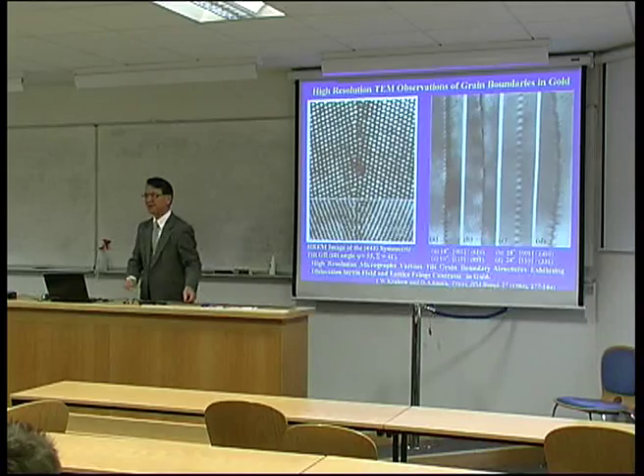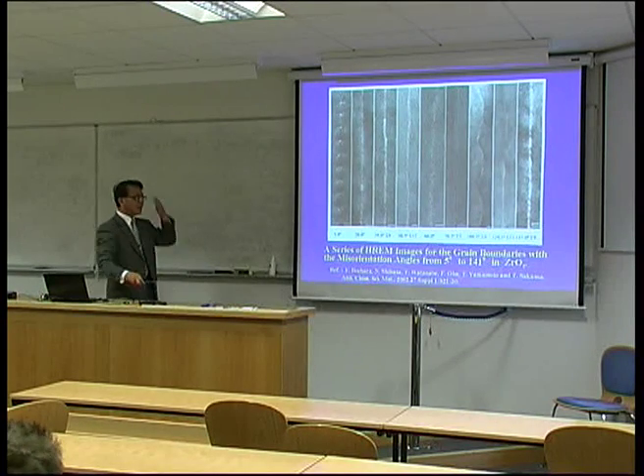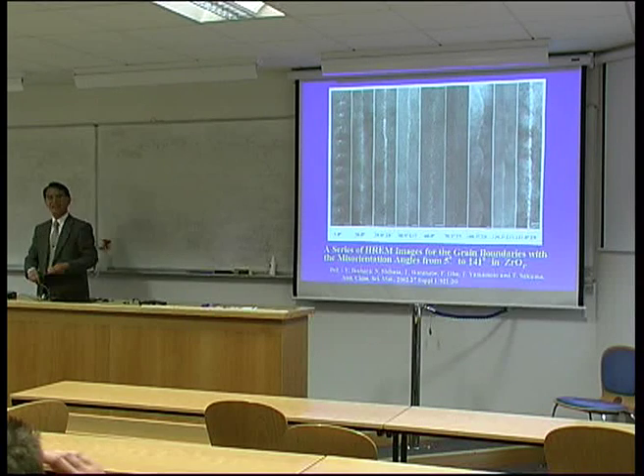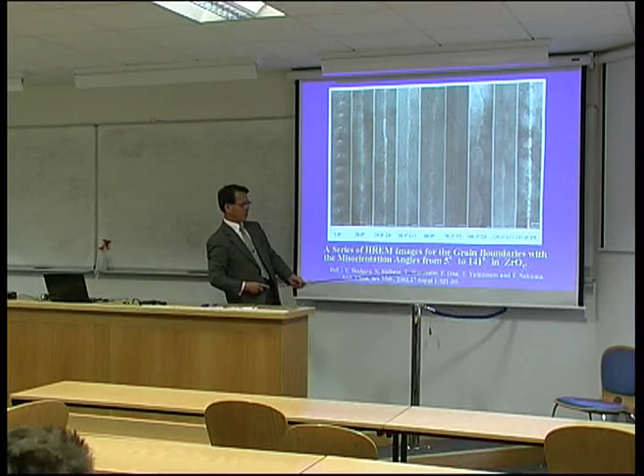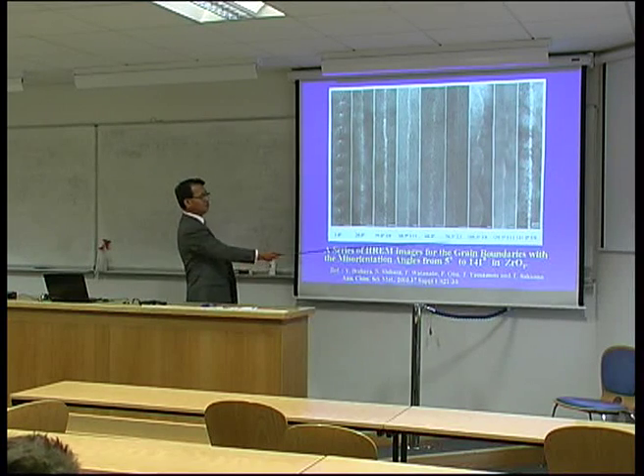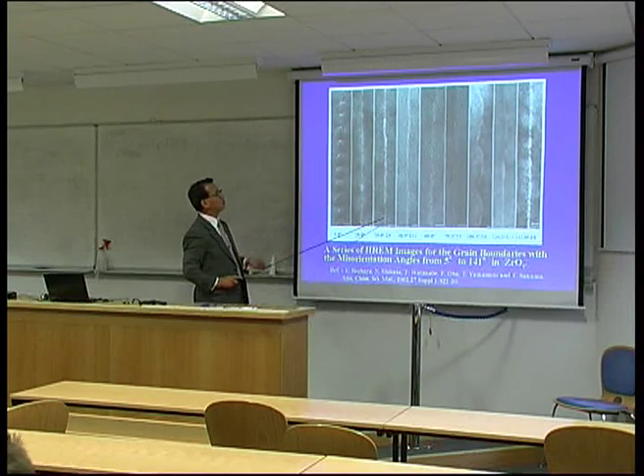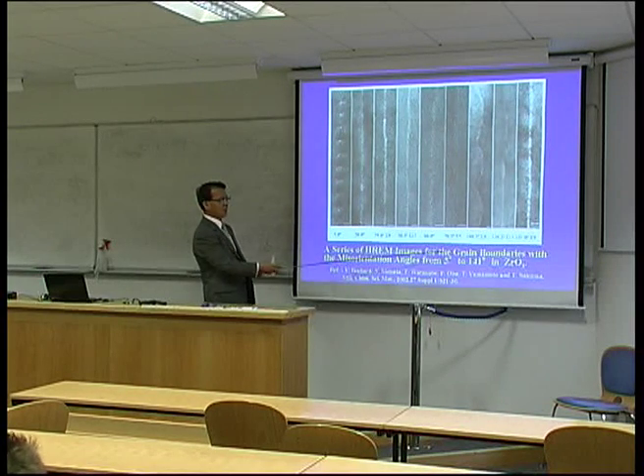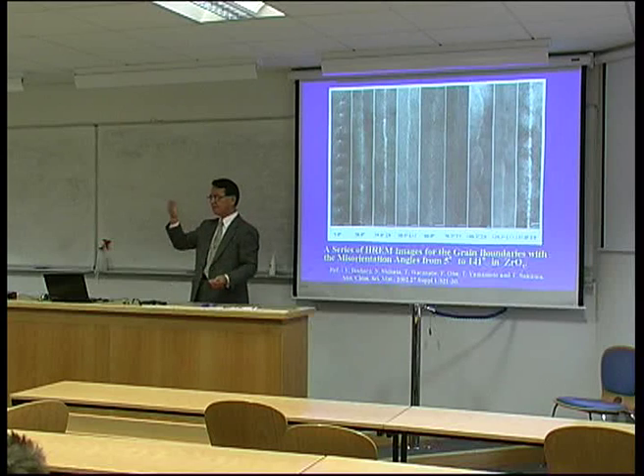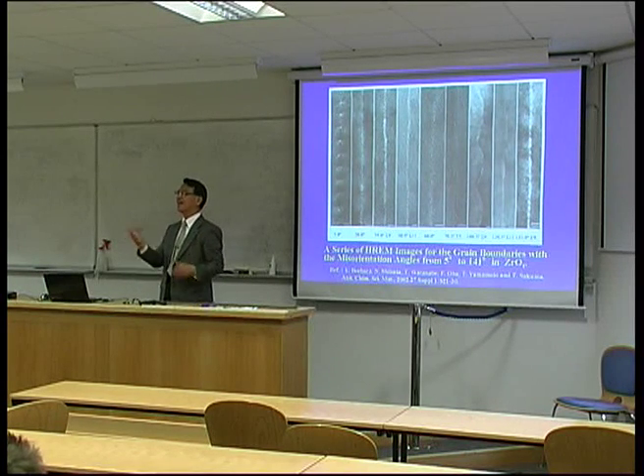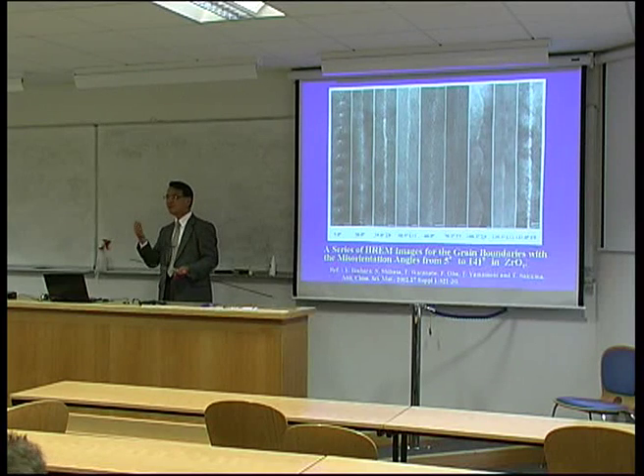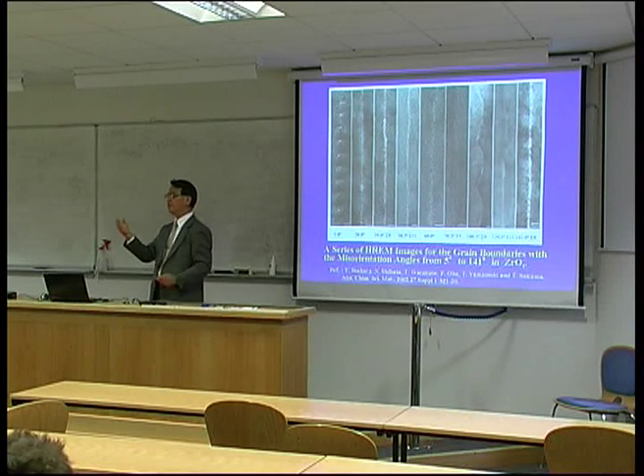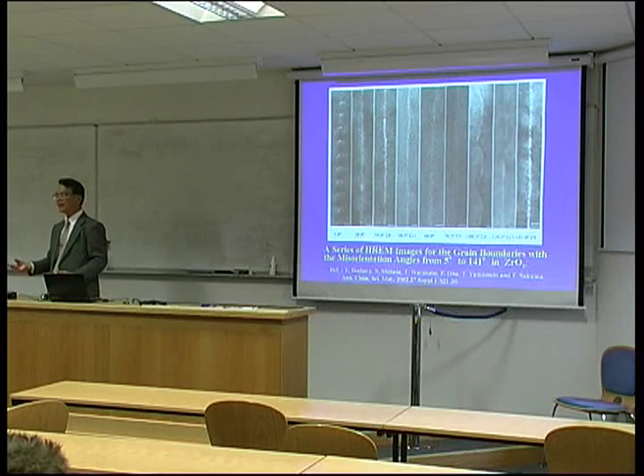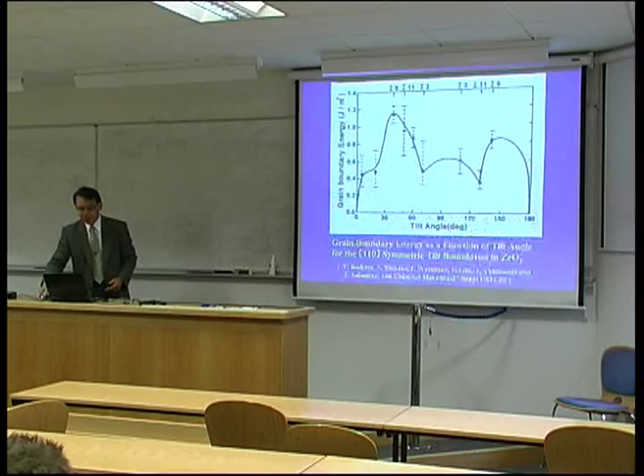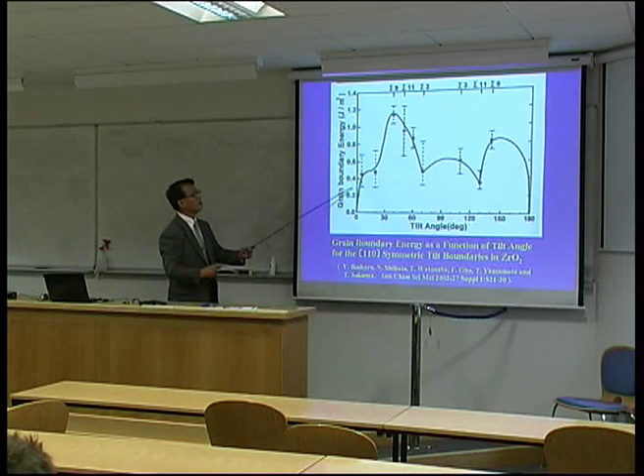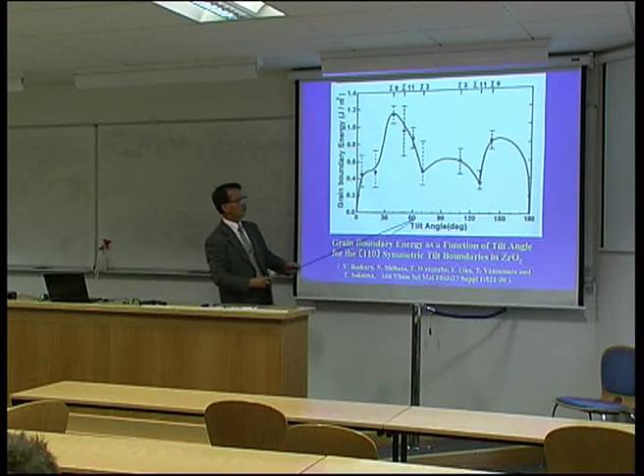This is the grain boundary under the microscope. Not only metallic material, nowadays we can even observe ceramics, this was just 2 or 3 years ago. Even the ceramics grain boundary, we can observe like this, zirconium oxides. So now grain boundary atomic structure is studied and observed more generally, not only in metallic material, even for semiconductor as well. So depending on such an atomistic structure, boundary energy can change as a function of its orientation.